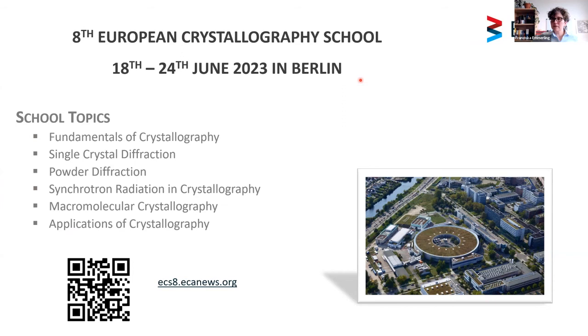It's not a super easy task, but software has also improved tremendously. Just to mention a few, there's DASH out there that is linked to the CCDC, and there's EXPO, from Italian colleagues, which I highly recommend when you go to metal organic frameworks, and there are other programs. So in some cases, you can also use your normal single crystal programs to solve the crystal structure. Just treat the powder diffraction data set as a super bad single crystal data set.